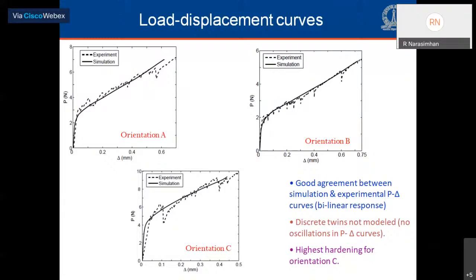One of the things that you can see in these experimental curves is some serrations in the load displacement curves. And these are associated with nucleation of discrete twins. So whenever a discrete twin nucleates, it leads to a drop in the load, and that is because of increase in tensile strain. That's not captured in the simulation because the simulation assumes twinning as a quasi-slip process.